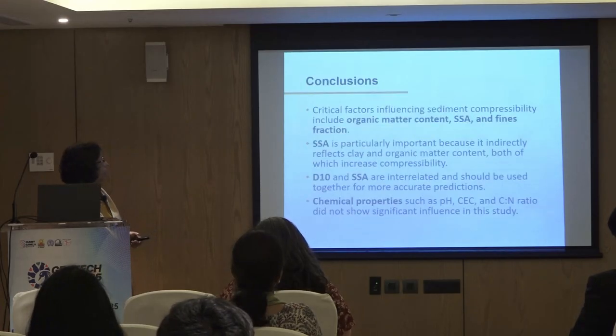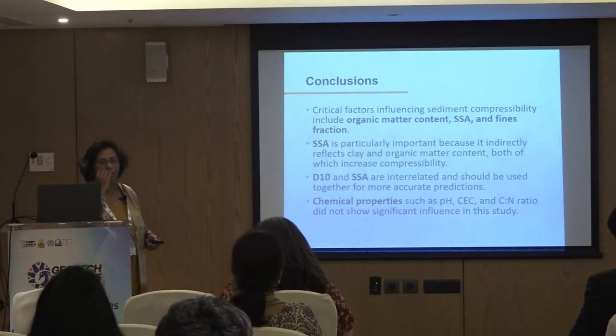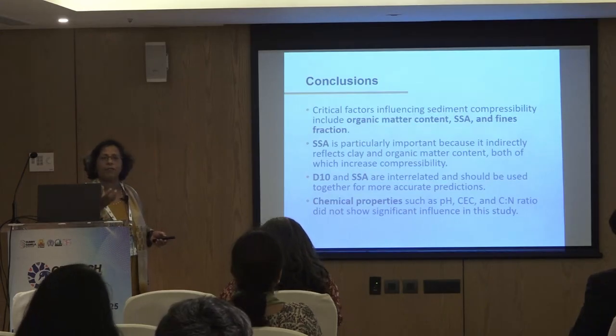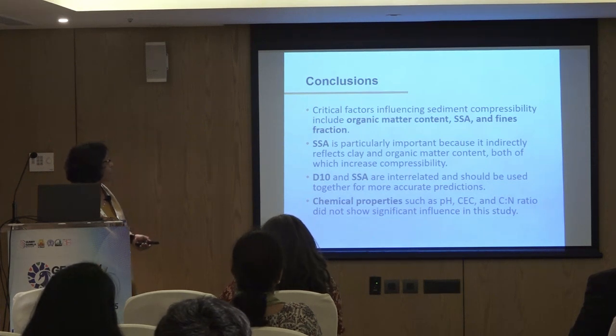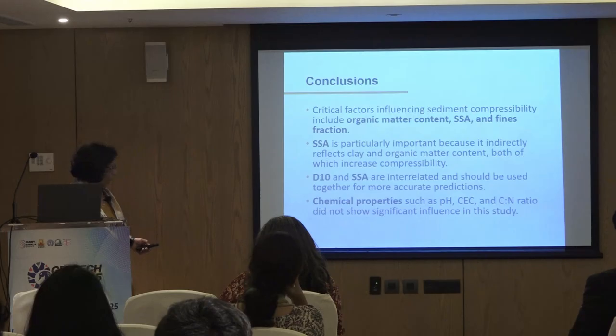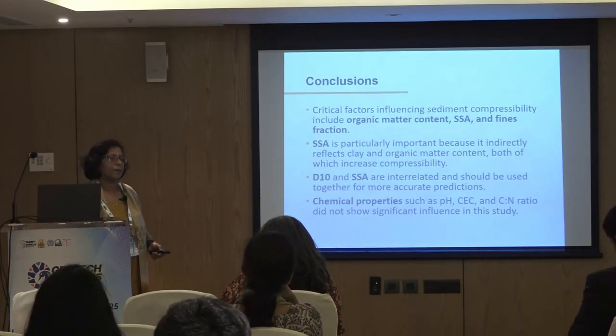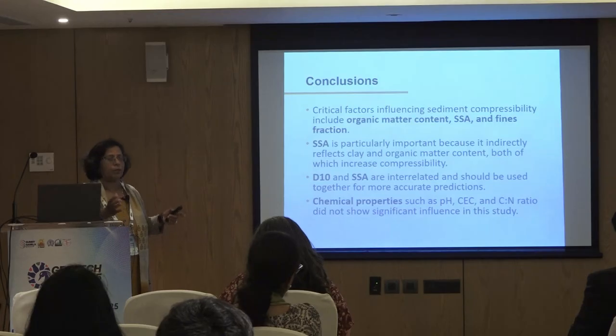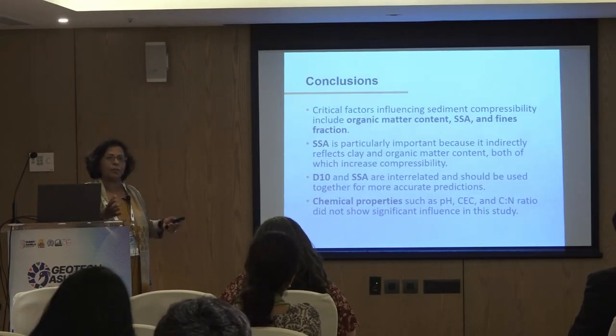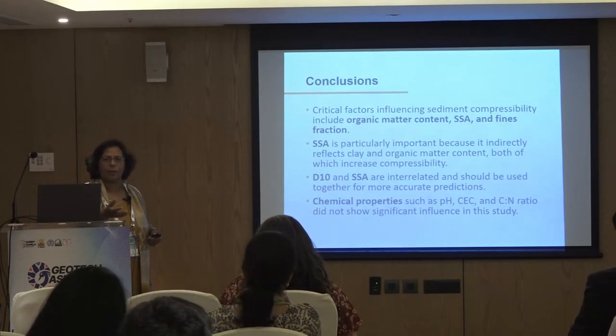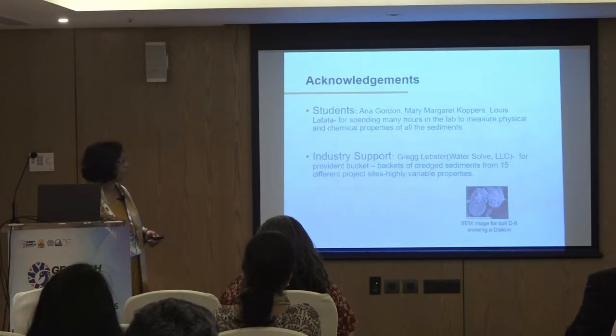So finally, the conclusion is organic matter, specific surface area, and fine content are important. We work with industry, which does very large projects. They still don't measure these properties, but at least they give an idea. Once you have sediment, you should pay attention to that. As I said, many of the chemical properties had very little effect. Now, this conclusion is based on 20 sediments, but extensive testing was done. We were hoping to find more relationship with chemical properties, but unfortunately we did not.